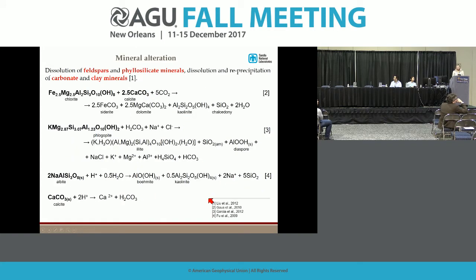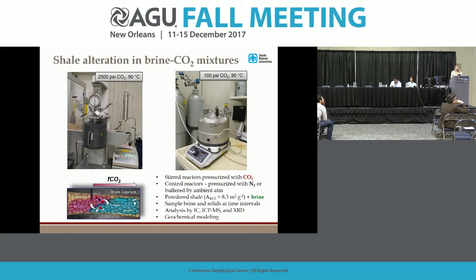but we have other shales as well to examine. So since I'm a geochemist, a few chemical reactions, I'm going to go really quick. The most typical reactions that people have both documented in laboratory studies and seen in the field due to injection of CO2 are dissolution of feldspars, phyllosilicate minerals, and carbonates. And carbonates, in particular calcite, has the fastest dissolution kinetics, and it's usually a significant component of shale. It could be up to a few weight percent. So dissolution of calcite can affect porosity at the shorter time scales. And I'm going to show some laboratory results.